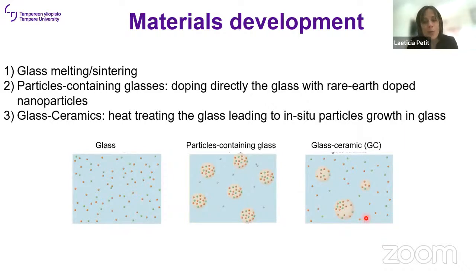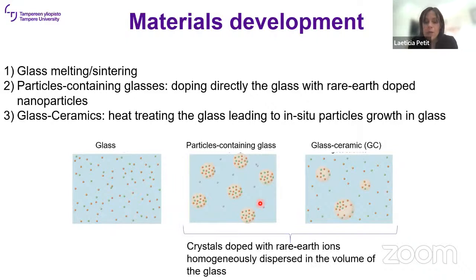And as we cannot control the crystallization process, as you will see in this presentation, we have worked on the direct doping method. We prepare crystals, we dope them with the rare earth ions that we want with the specific composition, and then we add them in the glass. So this is what I call particle containing glass. They are not glass ceramics. In both of these materials, what we try to have is crystal doped with the rare earth ions, and they should be homogeneously dispersed in the volume of the glass, and this is our target.